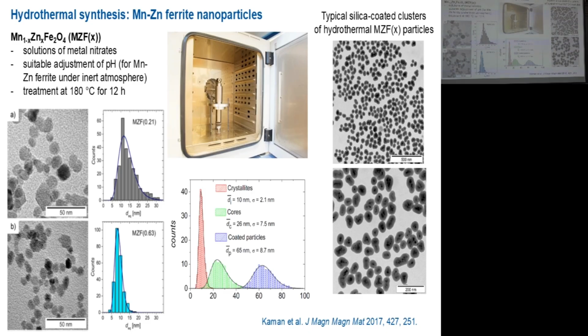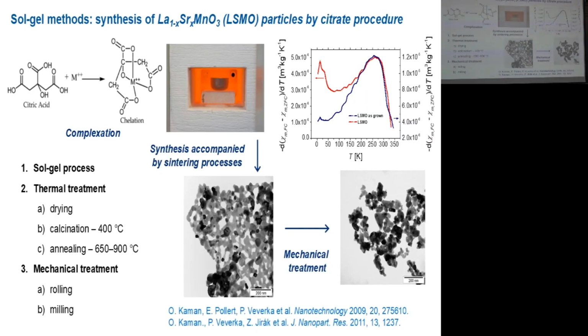And at the end, you will be able to heat these grains to do some chemical reaction, but the temperature needed for that will be significantly lower compared to the classical ceramic procedure. If you prepare some complex oxide from commercially available chemicals by the ceramic procedure, you need to mix the components thoroughly, and you need to apply high temperatures. But in this case, because of going through the gel and through the incineration of the gel, you will get such fine precursor that can be reacted at much lower temperatures.